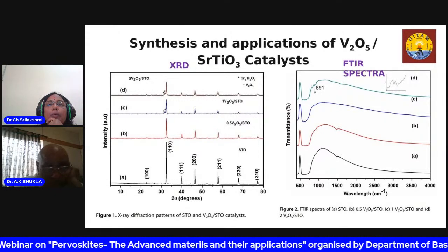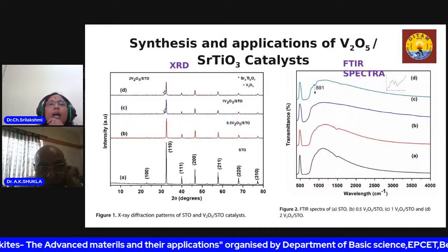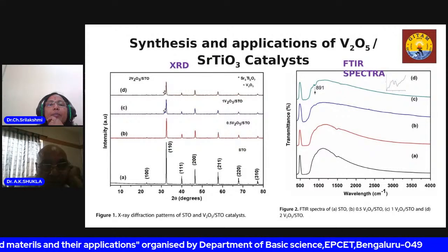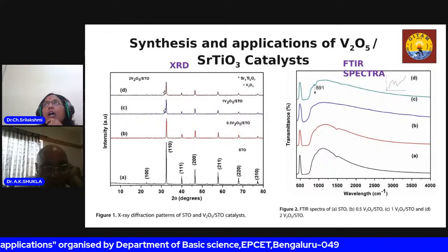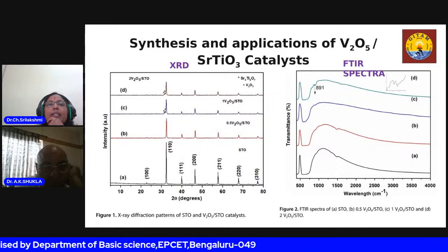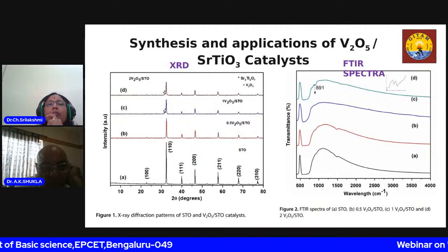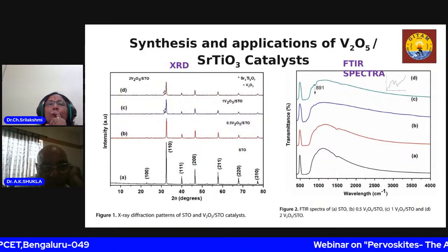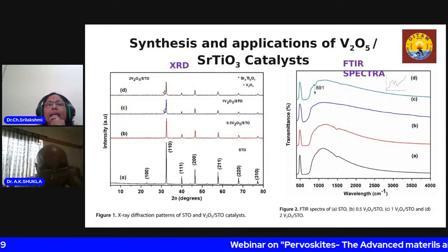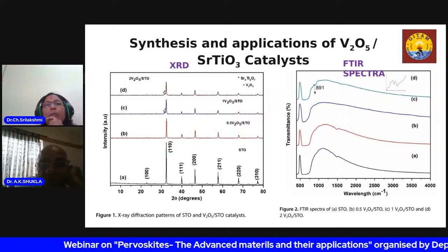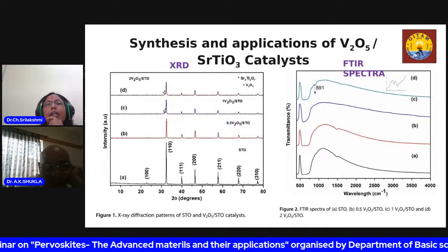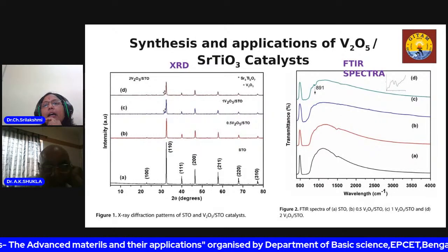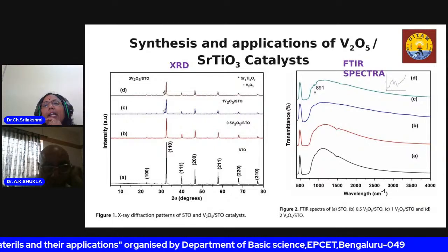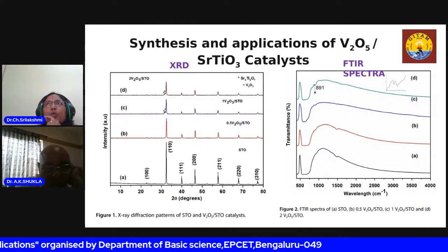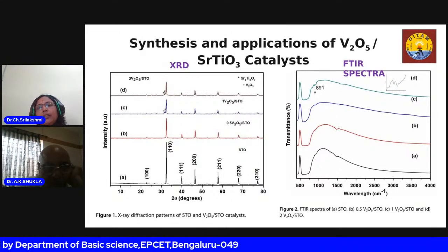With the incorporation of vanadium up to 1 weight percent, you can't really see the vanadium oxide. It means that at low concentration, vanadium is nicely dispersed in the pores of the strontium titanate. Only at high concentrations will it be seen. The presence of vanadium oxide is also seen very clearly in the IR spectra. The band at 891 corresponds to the V=O stretching vibration.